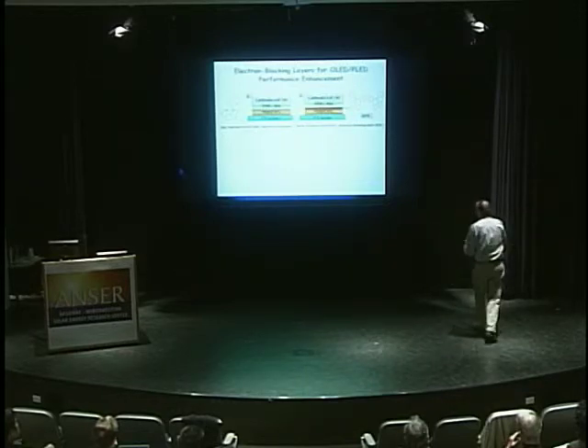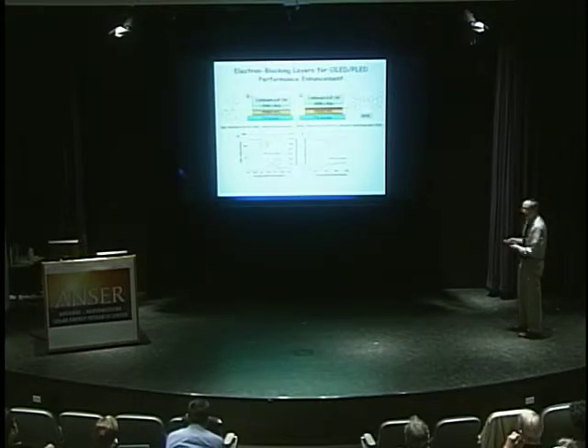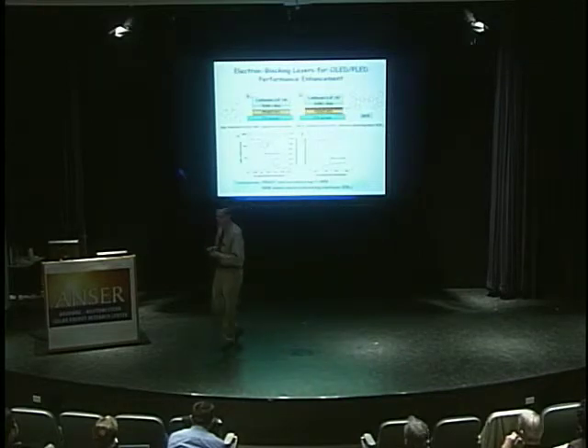And what do I mean by an electron blocker? Well, I blithely assume that the holes and electrons come from opposite directions in the OLED, meet, and give off light. Suppose they miss each other. Well, if the electron gets to the anode, I've wasted a lot of energy. So the thought was that if this blocked the electrons from getting to the anode, they would wait and help suck in more holes. And in fact, it works beautifully. So this is light output, this is current efficiency, and you notice in each case, with the electron blocking layer, you get a much higher efficiency. And one of the implications is that PEDOT, among all its failings, electrically inhomogeneous, corrosive, all of that, also is not nearly as good an electron blocker as a lot of people thought.